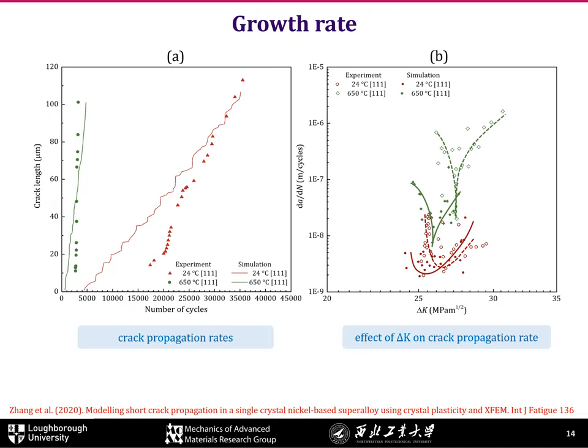Finally, crack lengths are correlated to the number of cycles. The numerical results have been scaled up to enable direct comparison with experimental results, and the overall trends are consistent with the experiment. The numerical curves present a step-change shape with increasing loading cycles, exhibiting the same response as experimental results — attributed to the multiple deflected crack path. The crack propagation rate da/dN was also correlated to the range of stress intensity factor ΔK, and the results show the same trend as in experiments: a deceleration followed by an acceleration in crack growth rate.